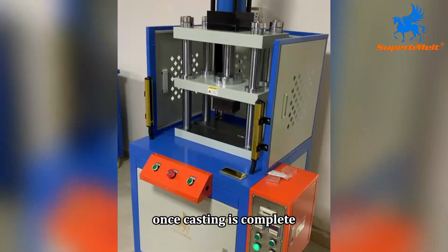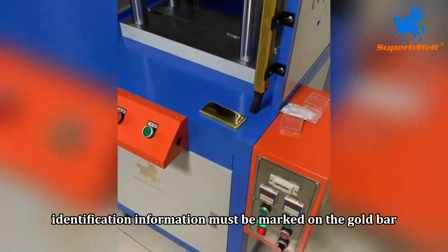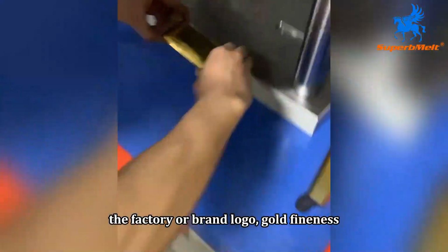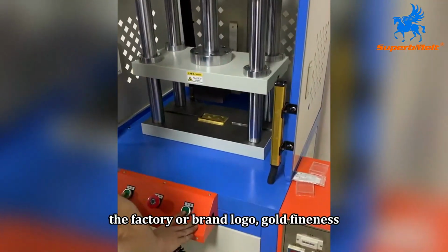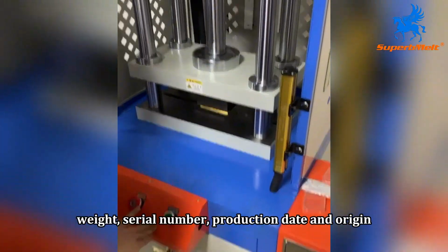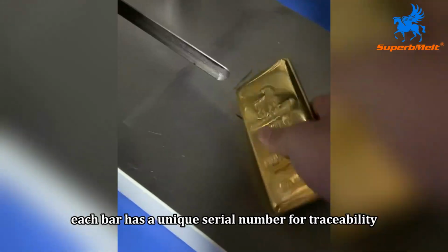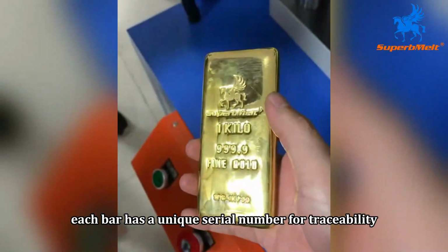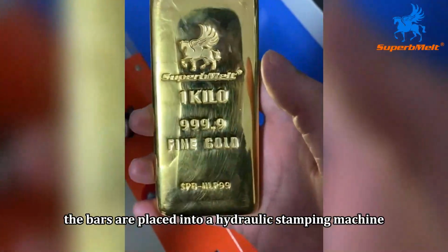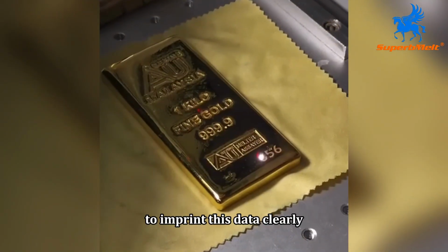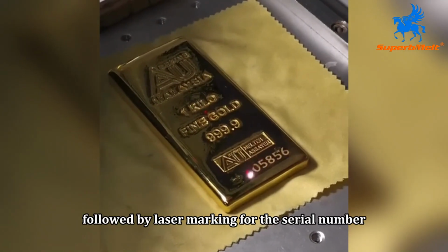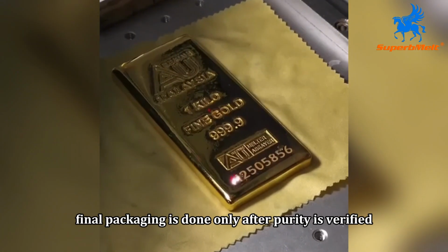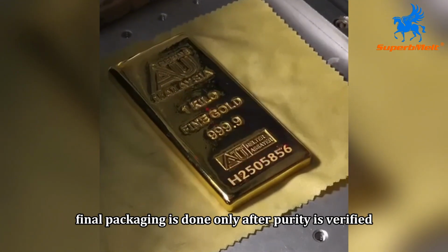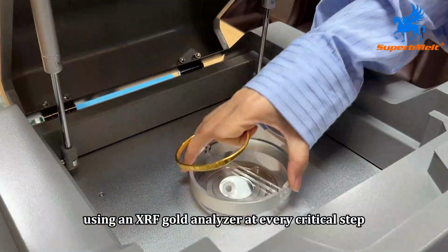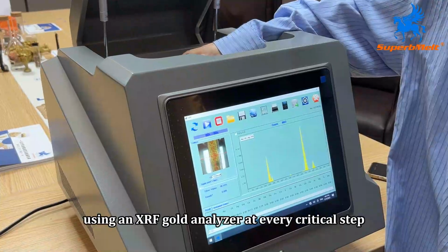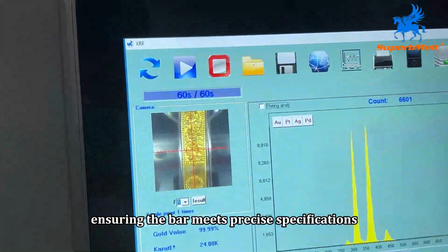Once casting is complete, identification information must be marked on the gold bar: the factory or brand logo, gold fineness, weight, serial number, production date, and origin. Each bar has a unique serial number for traceability and authentication. The bars are placed into a hydraulic stamping machine to imprint this data clearly, followed by laser marking for the serial number. Final packaging is done only after purity is verified using an XRF gold analyzer at every critical step, ensuring the bar meets precise specifications.